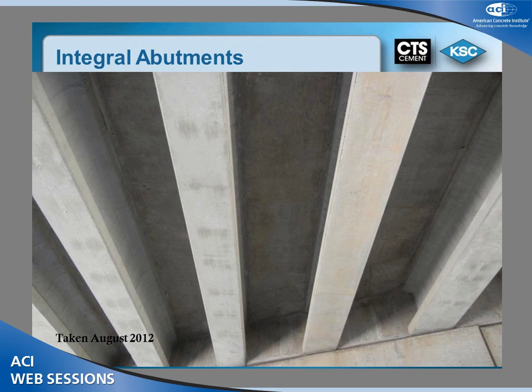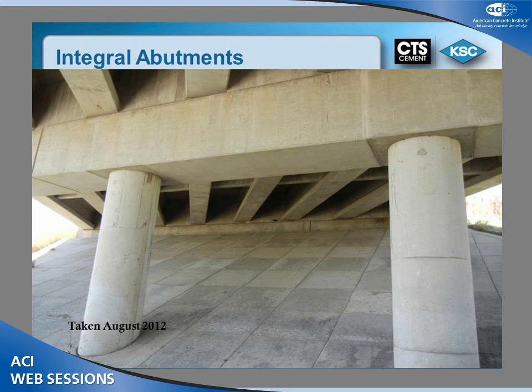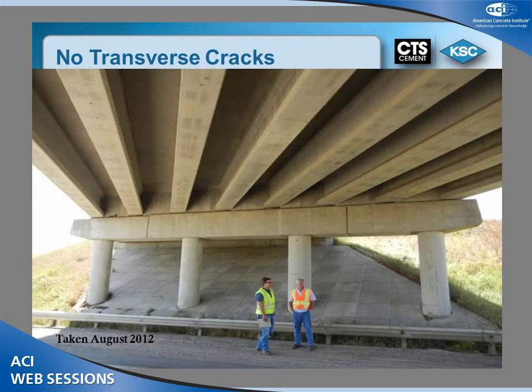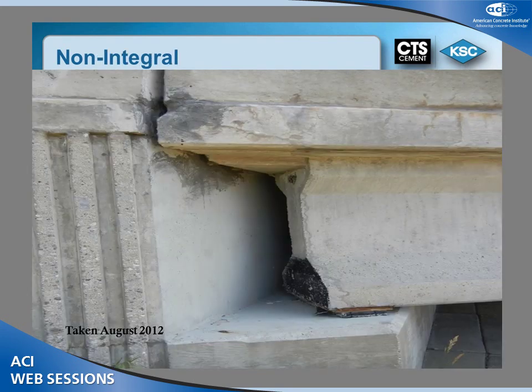This is really evident when you start looking at voided decks or box decks, where cracks actually radiate up at an angle from the abutment into the deck, just very well spaced, every 4 to 6 feet. This is just another couple of pictures of the abutments here, the integral abutment. And you can see there's no cracks up between the concrete girders. This is actually pictures of a bridge that was cast in 1996 in Michigan.